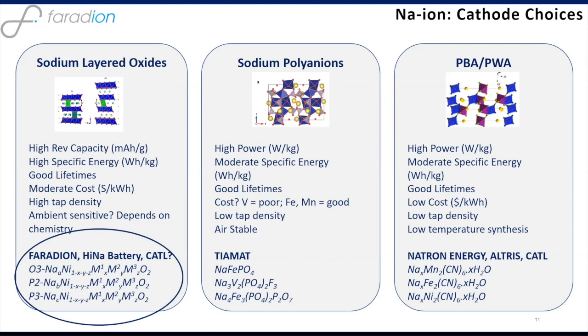I'll draw your attention to the fact also that the sodium layered oxides allow you much more flexibility in the structural types that you can use, much more than you can have in the lithium space. All of the lithium materials that are currently used, NMC and NCA, belong to the O3 structural type. But in sodium layered oxides, because of the change in the ionic radii of the sodium ion, you can also make materials called P2 and P3 materials. And in fact, what Faradion has done is taken advantage of this flexibility and formulated many biphasic materials, mixed phase cathode active materials that give you this benefit of the O3 and the P2 structures.